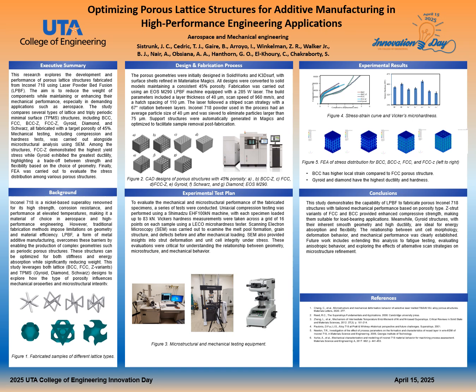Now, let's talk about the results. Among the lattice structures, FCCZ showed the highest yield strength at 965 megapascal, followed by BCCZ at 946 megapascal. These Z strut variants clearly offered improved mechanical resistance because the vertical Z struts enhance load-bearing capacity.